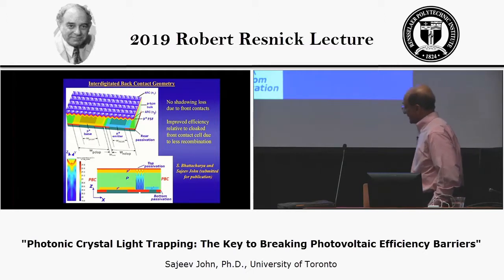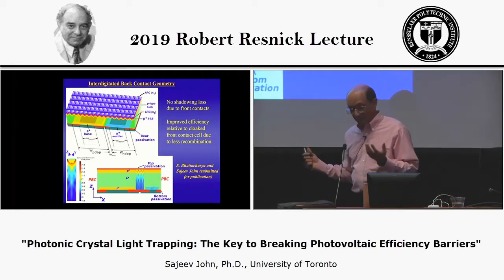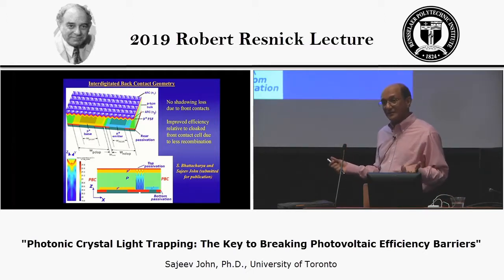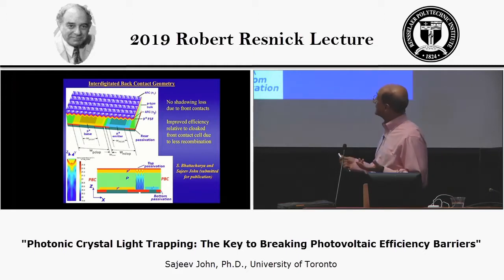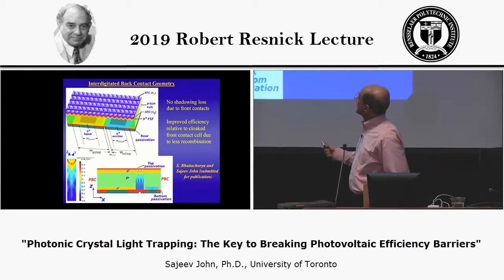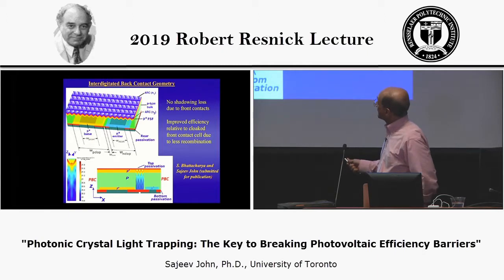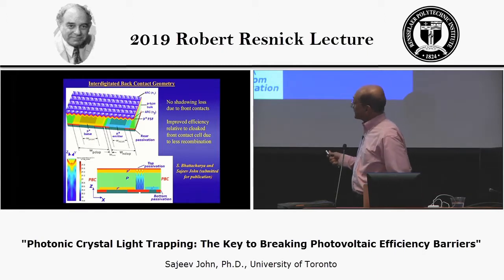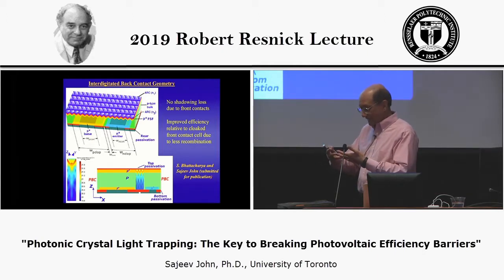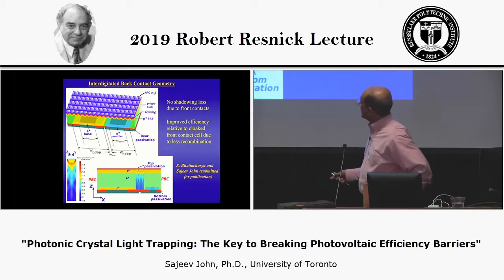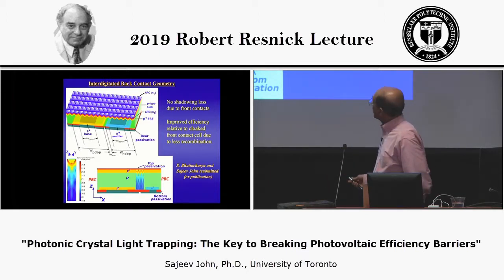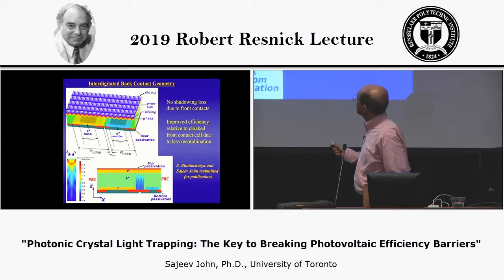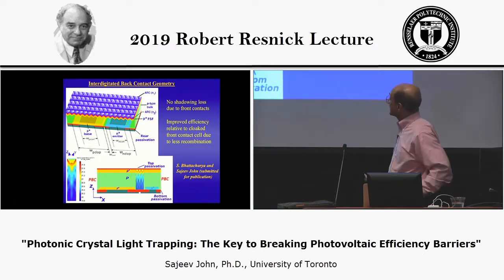Another design, which is the type of architecture used in the current world record cell by Kaneka, is to not have any contacts at the top at all, but to have all the contacts on the bottom in an interdigitated fashion, so they're alternating N and P type contacts. So there's no shadowing loss at all, and you can optimize the width of the P and the N contacts to minimize the recombination loss here.